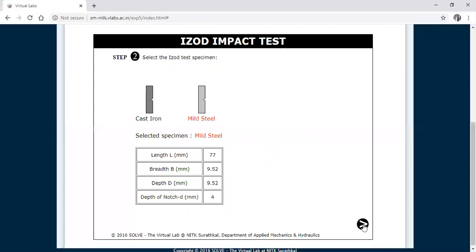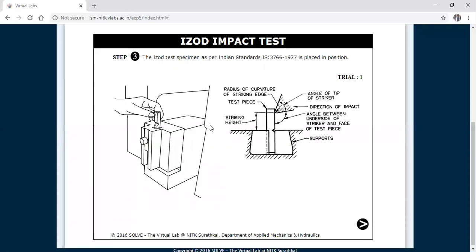Click the arrow mark again. This is where you mount the specimen. The specimen needs to be mounted in a cantilever position — fixed at one end and free at the other. While fixing the specimen, the V-notch must always face towards the striker. This is the striker position, and the striker is going to hit the specimen. The angle of the V-groove is 45 degrees.